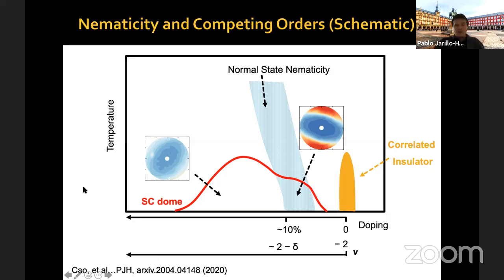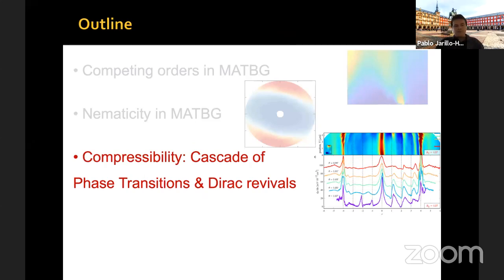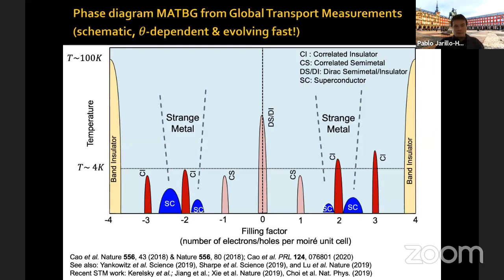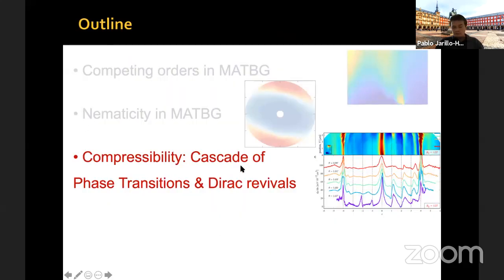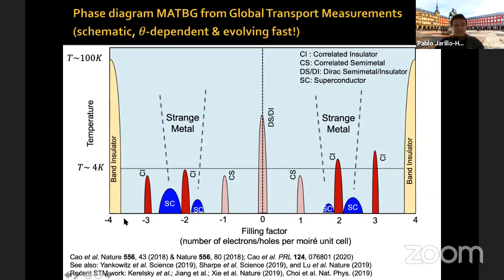Now, in the last few minutes, let me tell you about some of our other recent work. I should mention, by the way, that this work is done in very close collaboration with the group of Shahal Ilani at the Weizmann Institute and our theory colleagues there. So this is again a phase diagram of magic angle graphene, just a slightly different version. Here I'm showing that at each integer filling you have interesting correlated insulator or correlated semimetal, Dirac semimetal, Dirac insulator states. This depends on a number of parameters. In general, most of these energy scales are of order 4 K; in particular, superconductivity is always seen below 4 K. And the band insulator behavior occurs at a typical energy scale of 100 Kelvin, a bit larger.